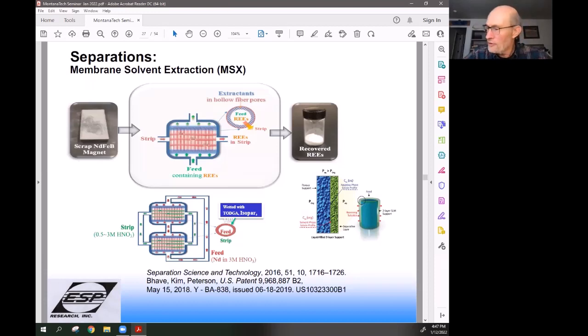Another way to approach this is not a red herring, but a different way of approaching membrane solvent extraction, which is by adding a porous membrane that contains the solvent extractant. You run your feed solution across that solvent extractant that's contained in the membrane, and you run your stripper on the other side. Basically the solvent extractant becomes your transport medium for the elements. And so you take a two-step unit operation into a single-step unit operation.